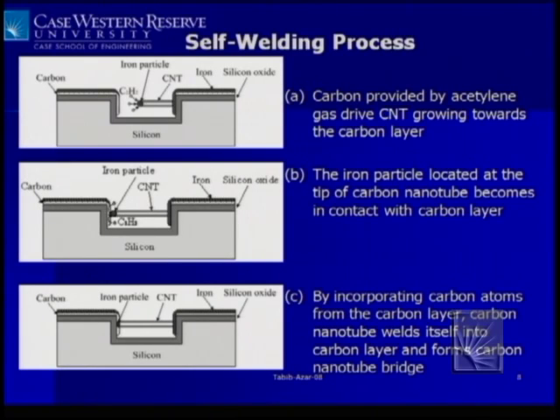And then the idea is that you put this device with these different layers on different walls inside your reactor and bring in carbon-carrying gases. The carbon-carrying gases can be anything. It can be methane, which is the cooking gas. It can be acetone. We can put a little bit of acetone inside the reactor, and as you heat it up, it starts evaporating. That can be your carbon-carrying gas. Actually, you don't need much, because just when we talk, there are all these hydrocarbons and CO2 generated by biological systems. That's enough to grow these carbon nanotubes. So you don't need much carbon in the environment to grow them.